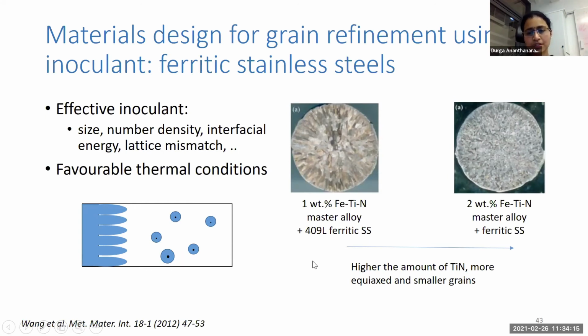So when we looked in literature about this ferritic stainless steel, we saw that adding titanium nitride, if it forms, can act as an inoculant. So here we see with more addition of titanium and nitrogen, we have finer and finer grains.